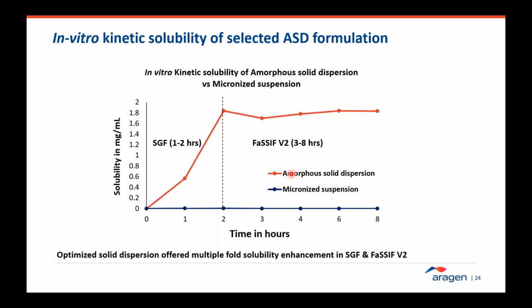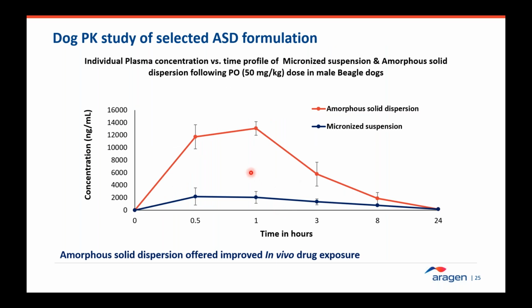And this formulation is typically subjected to rodent and non-rodent PK studies. And this is the dog PK data illustrated here over a 24-hour period. And so we see over 5 to 6 fold bioavailability or oral exposure improvement compared to the micronized suspension, which is typically adequate. As we increase the dose, a dose proportional increase could be observed up to a certain dose, and which usually enables the molecule to complete the tox studies at a desired exposure levels and also enable the smooth clinical studies with guaranteed exposure at the clinical doses.